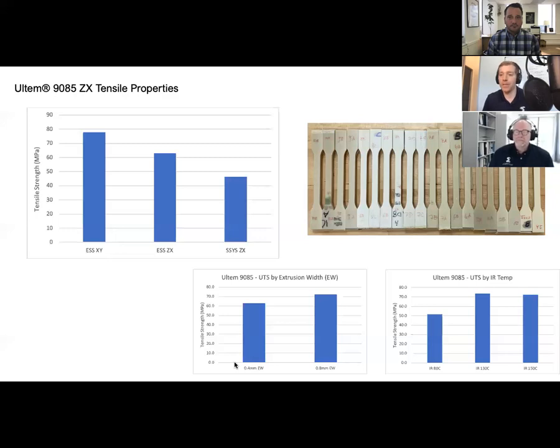With bigger nozzles, there's a lot more residual heat coming through into the part as you're printing it, and again we see increased layer bonding. I just wanted to highlight quickly that there are some unexpected gains to be had when you're printing faster, things that are not normally seen with an FDM type system.